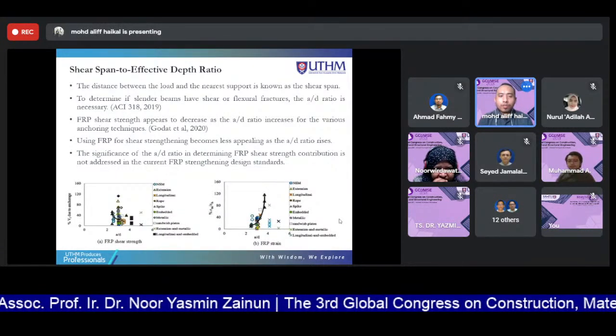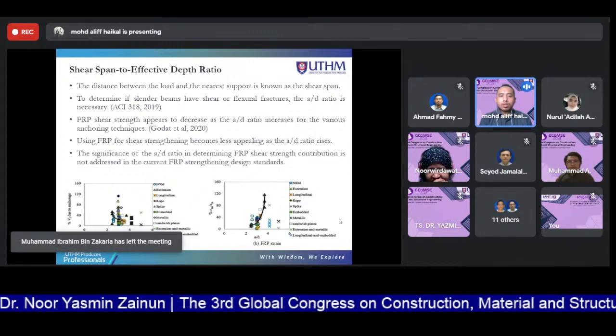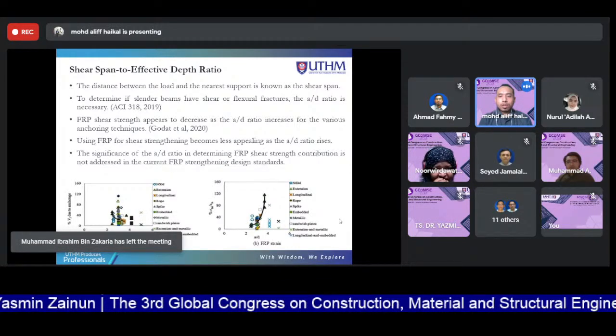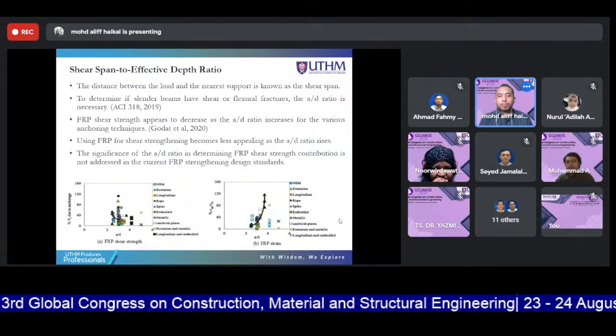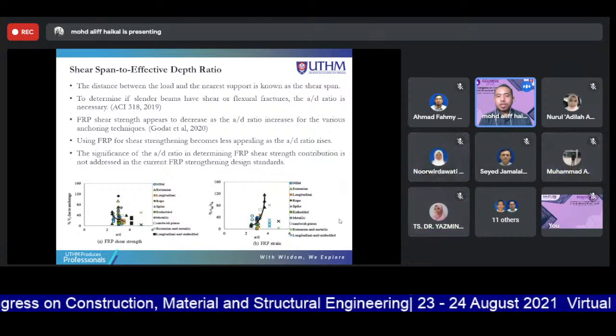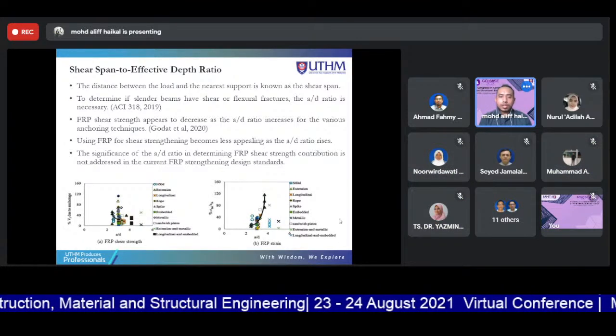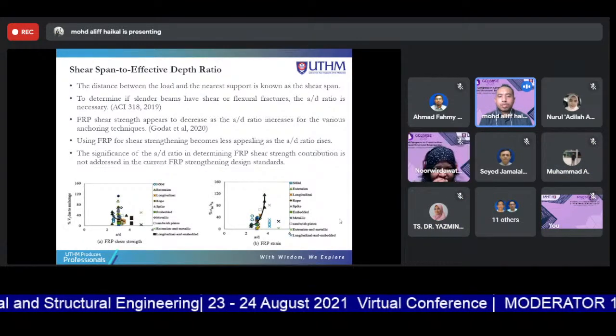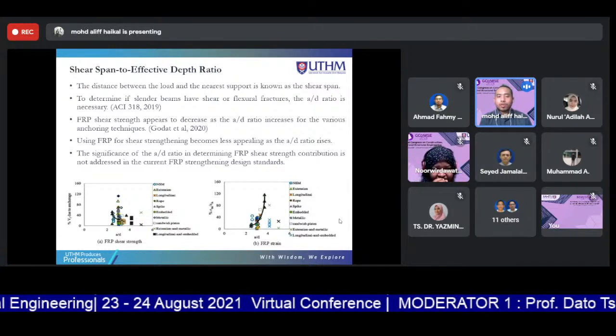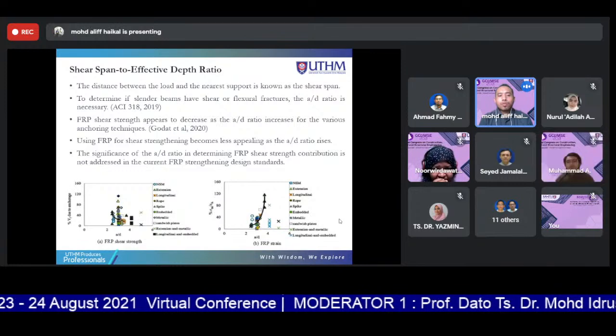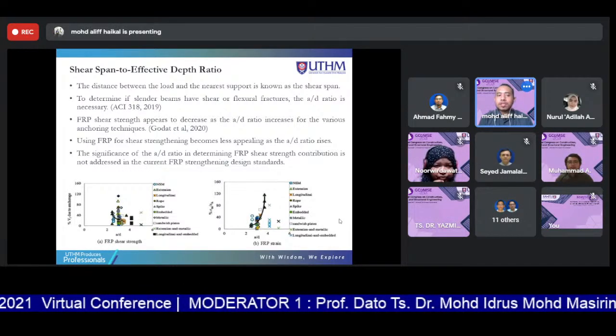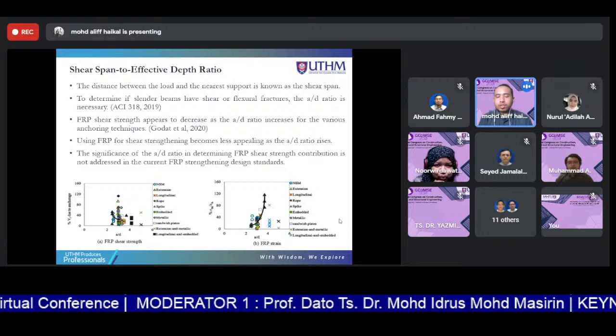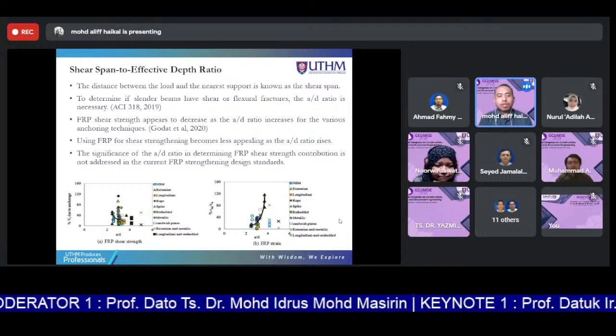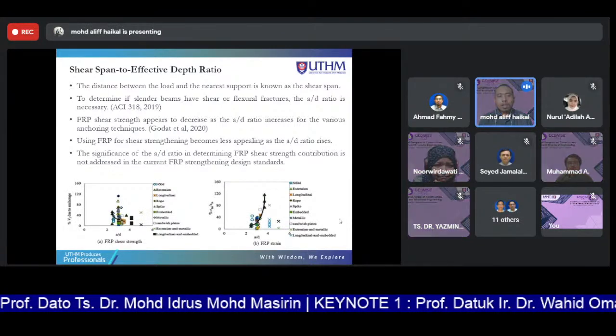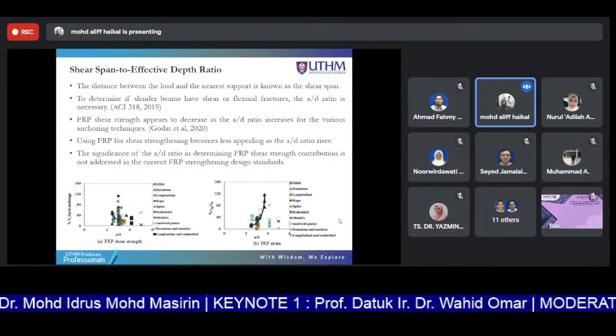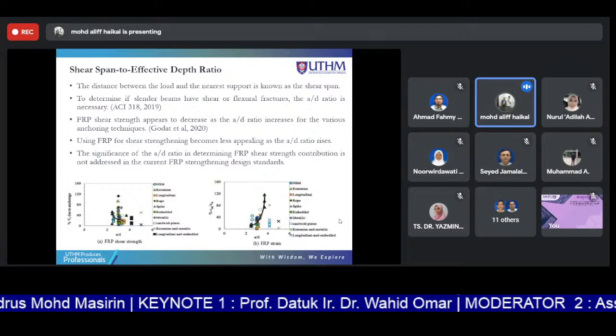Okay. For the shear span to effective depth ratio, the distance between the load and the nearest support is known as the shear span. To determine if slender beams have a shear or flexural fracture, the a/d ratio is necessary. FRP shear strength appears to decrease as the a/d ratio increases for the various anchoring techniques. Using FRP for shear strengthening becomes less effective as the shear span to effective depth ratio rises. The significance of the shear span to effective depth ratio in determining FRP shear strength contribution is not addressed in the current FRP strengthening design standards.